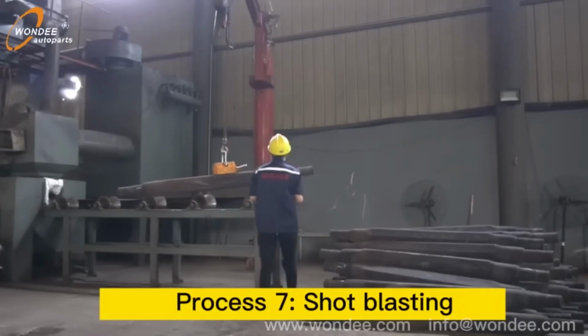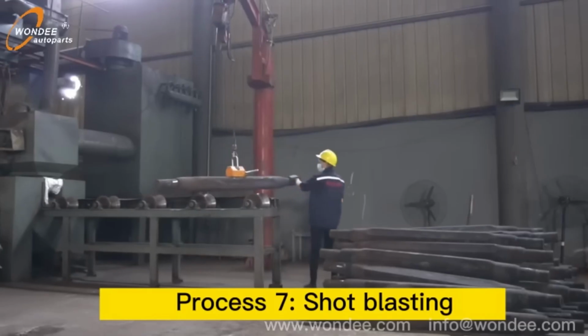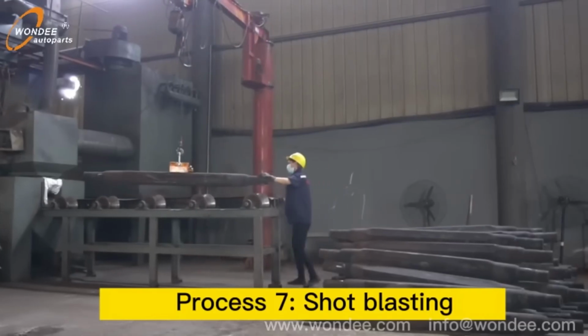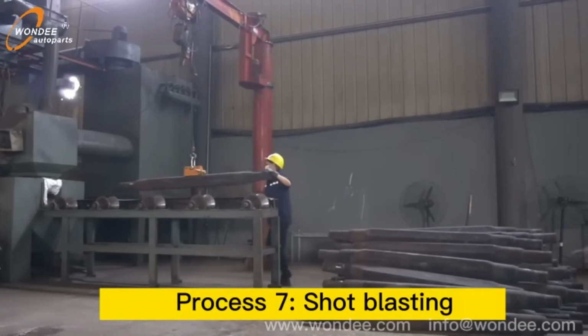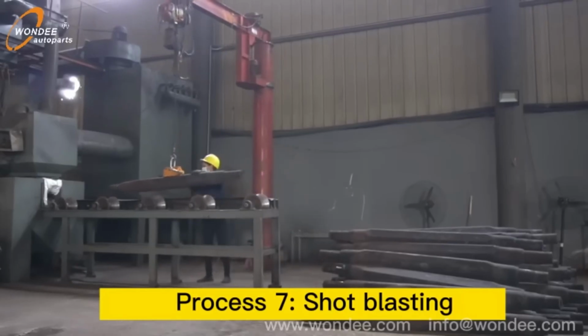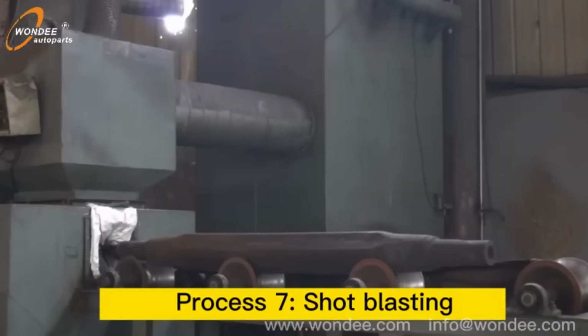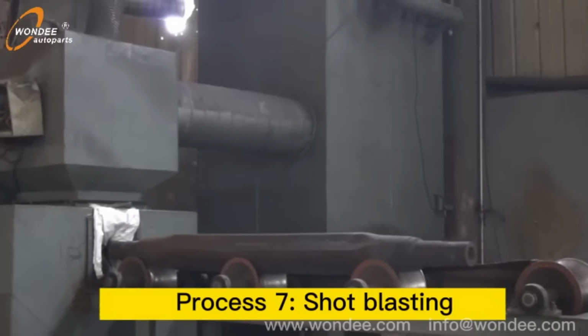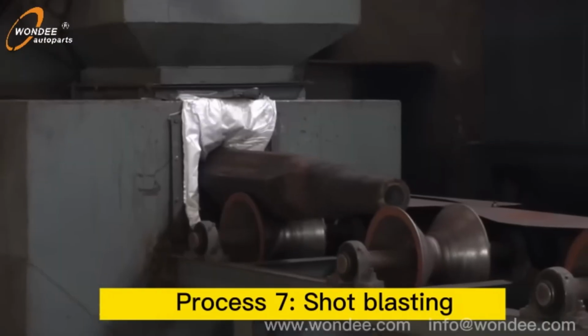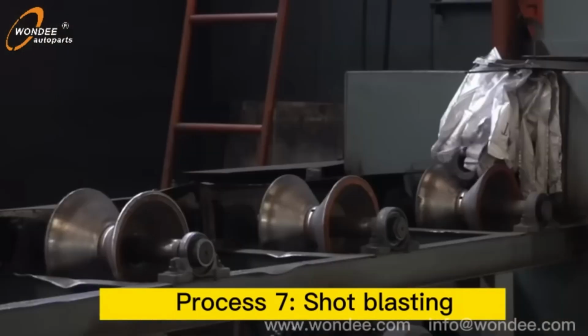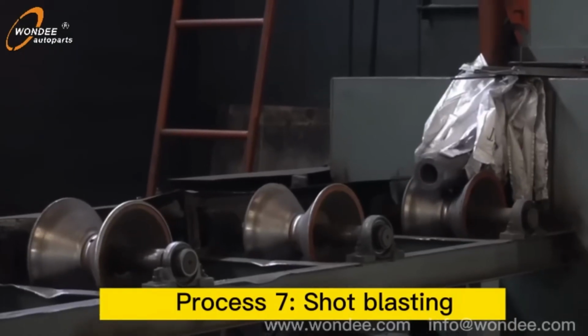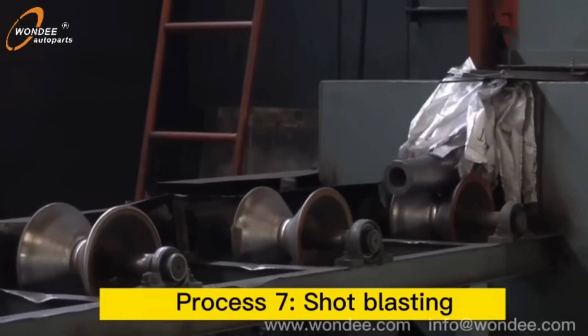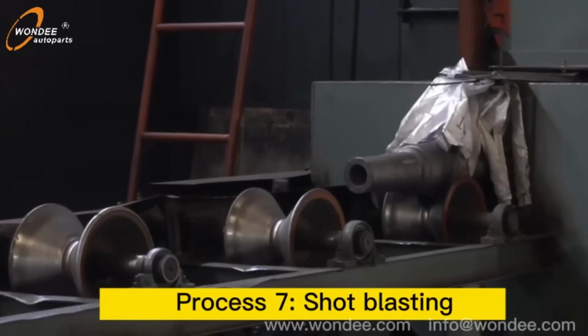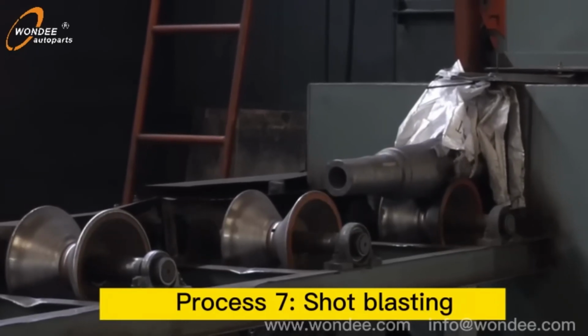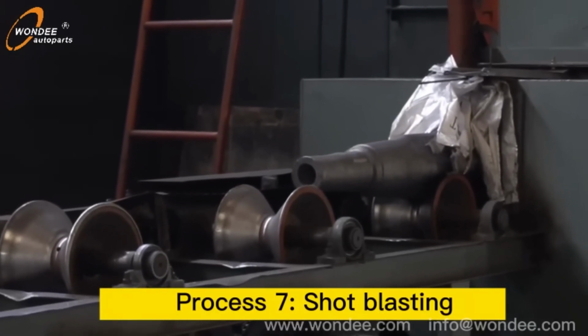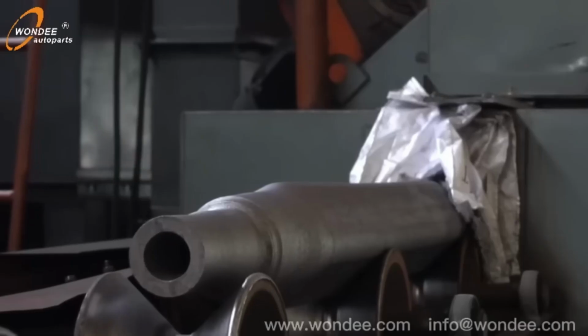Shot blasting is a mechanical surface cleaning process where high-speed steel shots or grit bombard the axle's surface, effectively removing mill-scale, rust, oxide layers, and heat treatment discoloration. The axle is placed in a blasting machine, where rotating turbines propel abrasive media under controlled pressure and speed. This not only cleans the surface, but also creates a uniform, slightly rough texture enhancing paint adhesion in later processes.